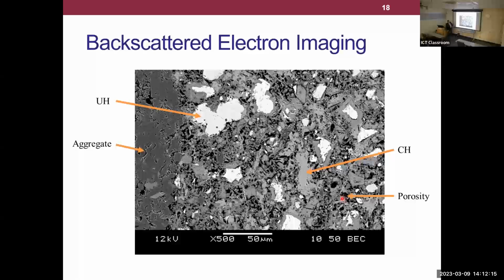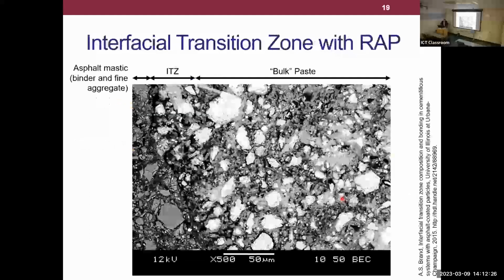Does the grayscale actually show up that well? I guess you can kind of see the color difference. It's a little bit difficult, but we use a computer to do image analysis. Here's an image of the RAP ITZ. Here you can definitely see asphalt mastic. You can see there are some aggregates in this binder, and you can clearly see that, which is why this image is very nice.